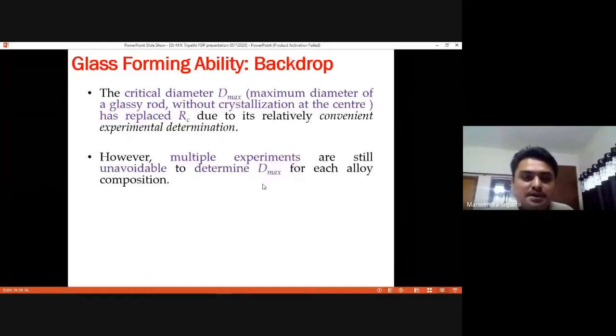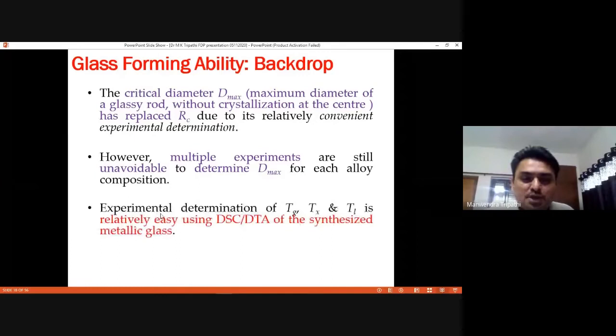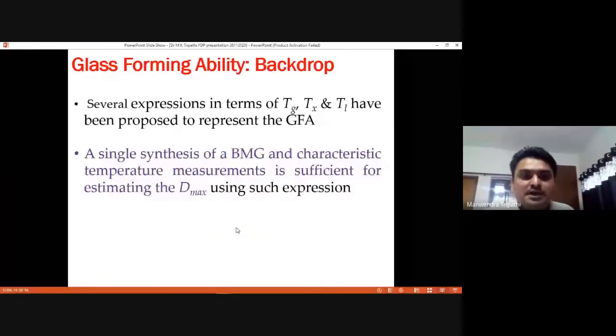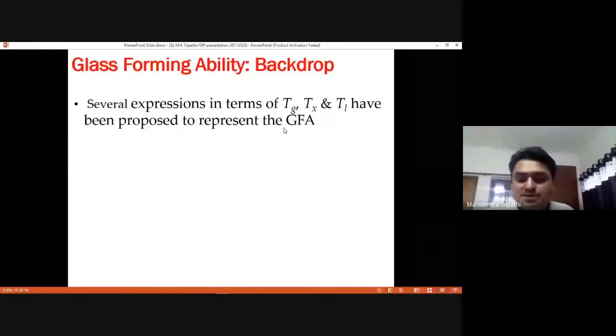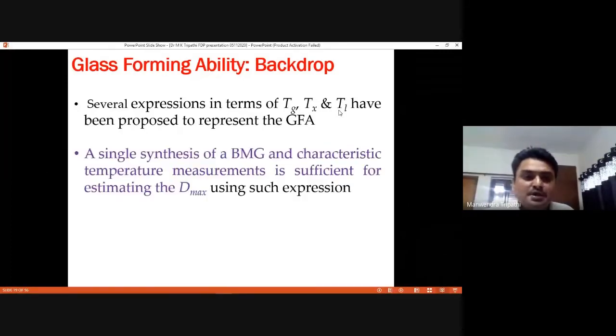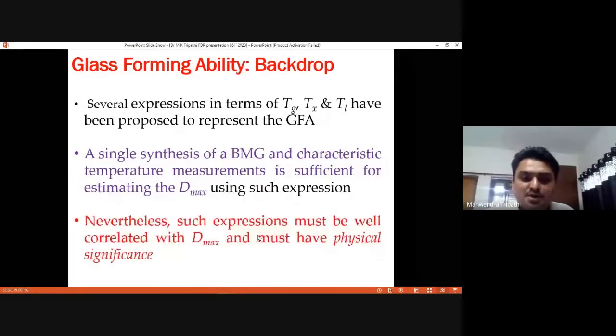But you can easily determine your Tg, Tx, and Tl experimentally using DSC and DTA, differential scanning calorimetry and differential thermal analysis. You can do it once you synthesize a metallic glass. So it is noted that several expressions in terms of Tg, Tx, and Tl have been proposed to represent GFA, because Tg, Tx, Tl represent the metallic glass irrespective of the cooling rate, right? A single synthesis of a BMG and its characteristic temperatures, Tg, Tx, Tl, is sufficient to estimate Dmax using such an expression. But the requirement is that such an expression must be very well correlated with Dmax and must have physical significance. What is the meaning of physical significance? I will explain it. But the correlation should be high first.